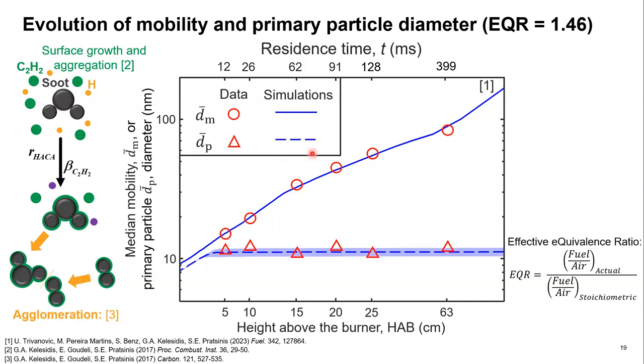Now, with the dashed line, we see the simulations of the primary particle diameter. And here the shaded area represents the stochastic variability between different simulations. And this is actually also present in the mobility diameter line. However, you cannot see it because it's relatively small and hidden by the log scale. So back to the primary particle simulations, we see that they are again in excellent agreement with our experimental data.